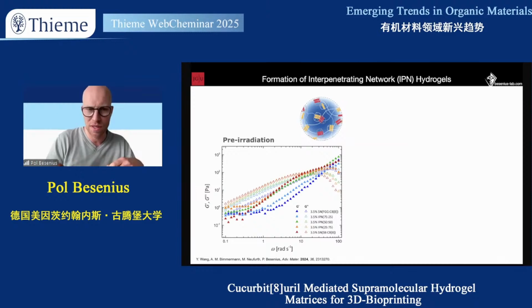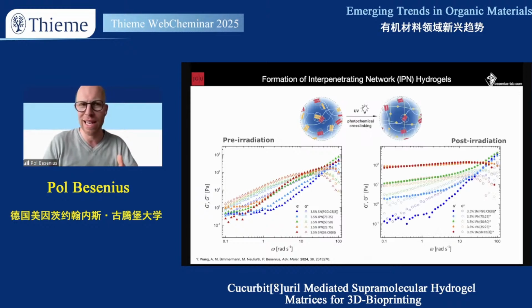And what you see here is a rheology graph in the presence of CB8, but before you shine light on that solution. So going from 100% tripeptide to 100% stilbazolium, and it's nothing but a superposition of the individual. You can hit a sweet spot where you do get some physical crosslinks that are non-reversible in combination with a dynamic character, and this is in between, so going from 3 to 1 to 1 to 3 ratio. That's exactly where that range is, where you can still operate with different degrees of covalent fixation. Let's call it fixation of the network.